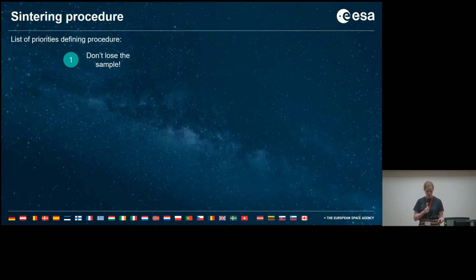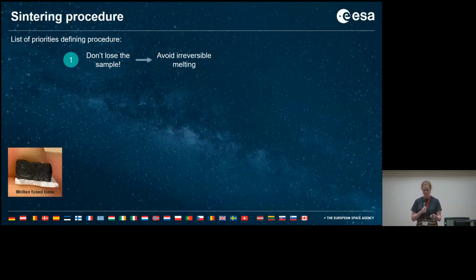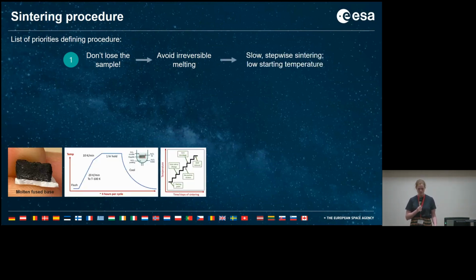So very quickly, the sintering procedure was defined by priorities. The first being, don't lose the sample. So we wanted to avoid irreversibly melting it to the crucible. And so we did a very slow, stepwise sintering process using traditional furnace sintering, slowly increasing the temperature each time and holding it 1 hour at each temperature and then analyzing the material.